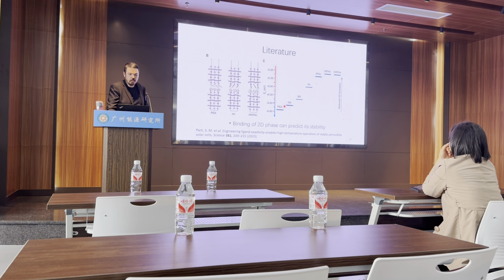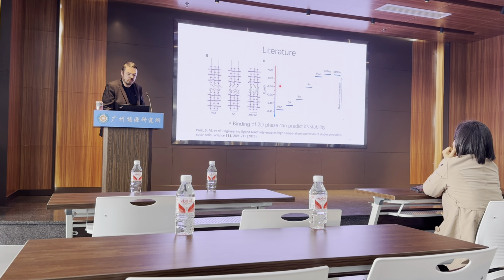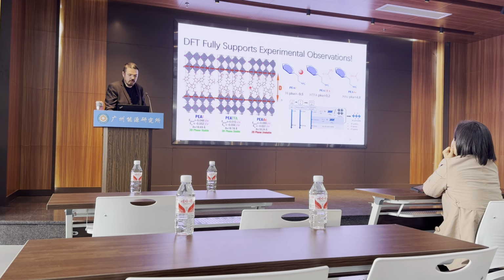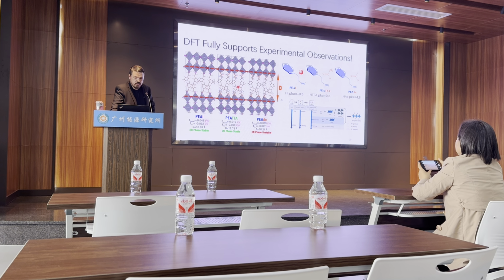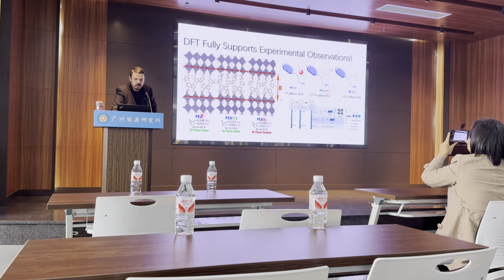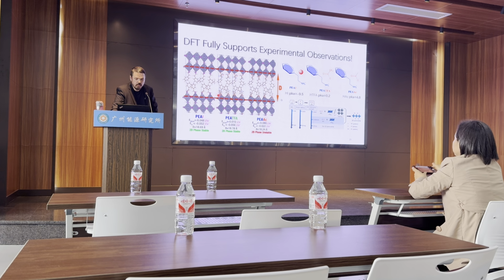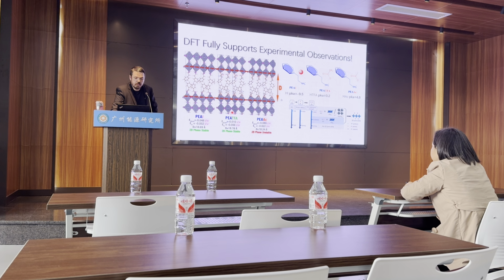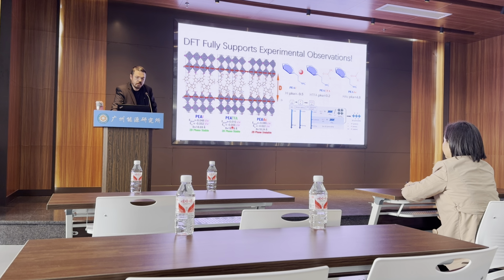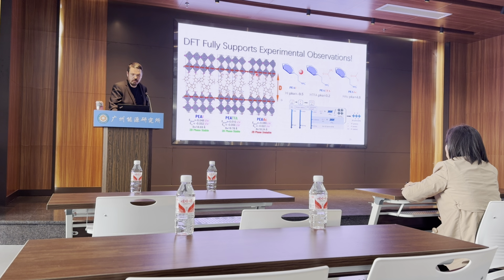As it becomes stronger in binding strength, the 2D phase becomes more stable. So DFT actually predicts the stability pretty well. This paper demonstrated that very well. And fortunately, our results are in agreement with experiments and previous papers. You can see that in this case, the iodine-based one binds the strongest when we look at the binding strength. The TFA one is intermediate, binds somewhat strongly, still stable but not as stable. And the one based on acetic acid is not stable at all. So experiment and our results are in agreement.